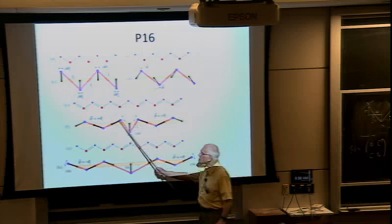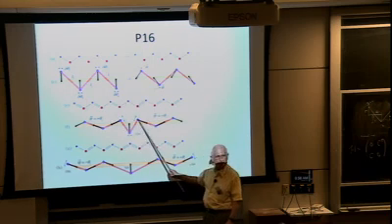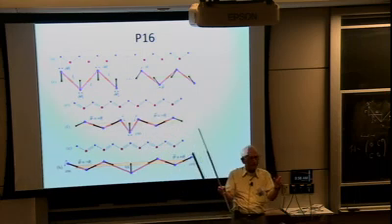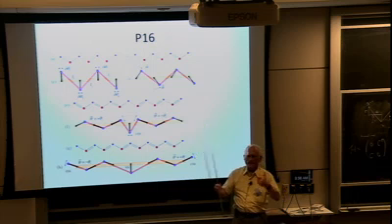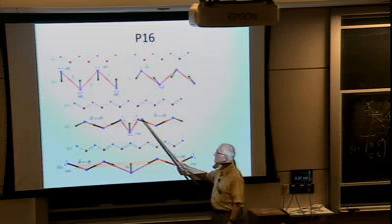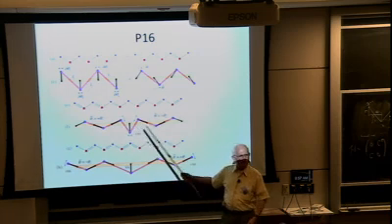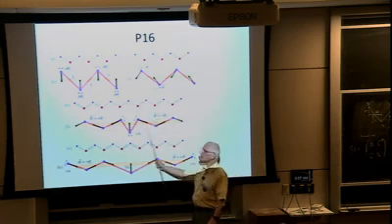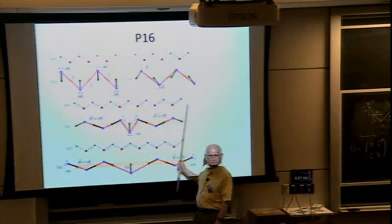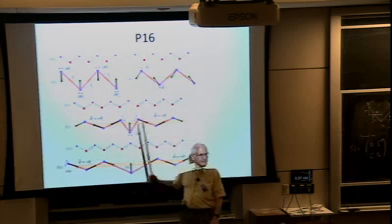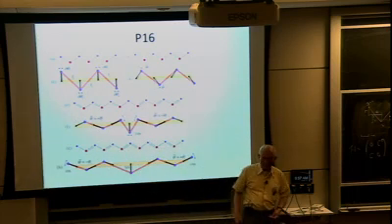Or I could alternatively have connected it like this. I didn't draw it in the picture. Then I only have one bond, but I have two independent variables. But remember, the overall magnitude of the two doesn't matter, so really I just have the ratio. I have one variable that can match the constraint of this. So there's a counting argument. If we know how many zero modes we have going this way, we know how many amplitudes we have in that direction, we have the number in that direction, and we're guaranteed to get a zero mode in the middle.